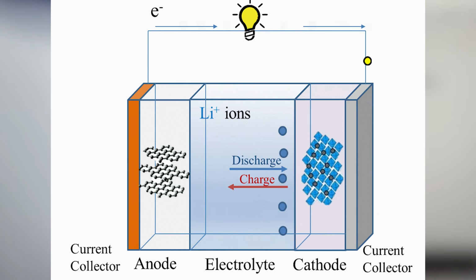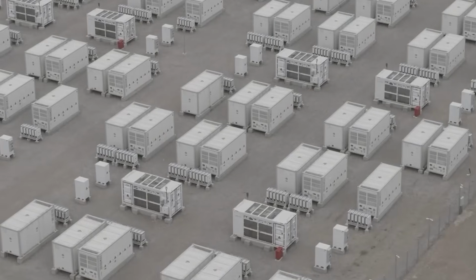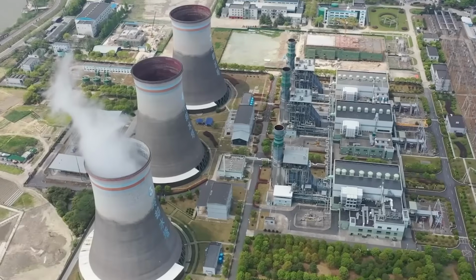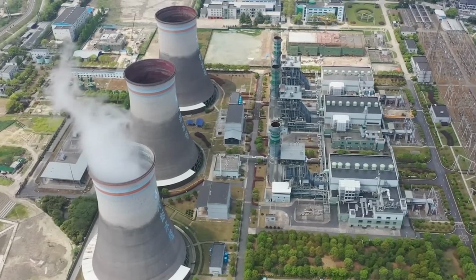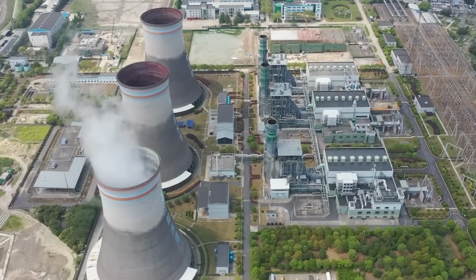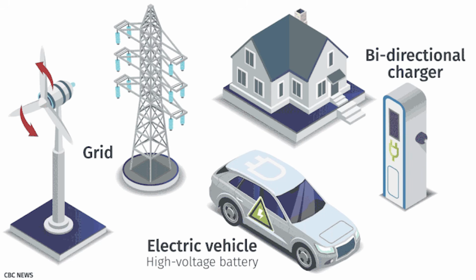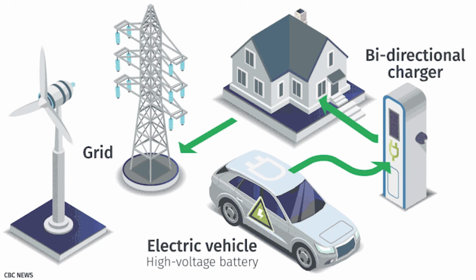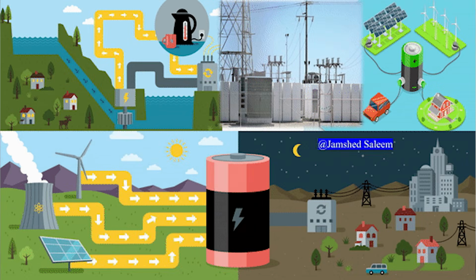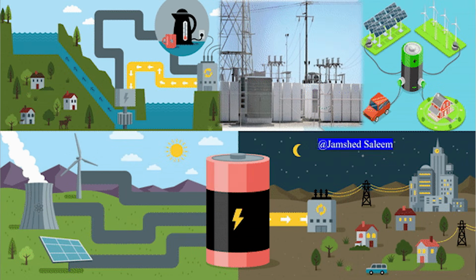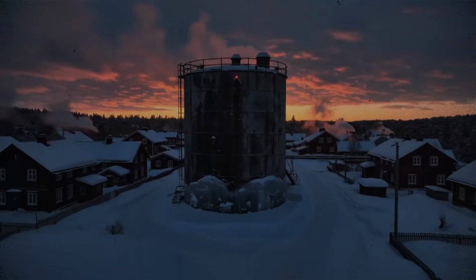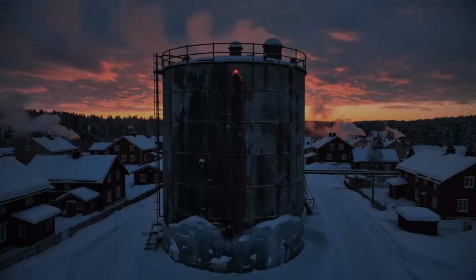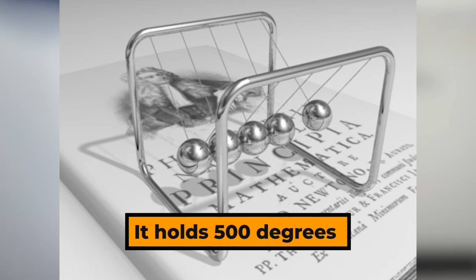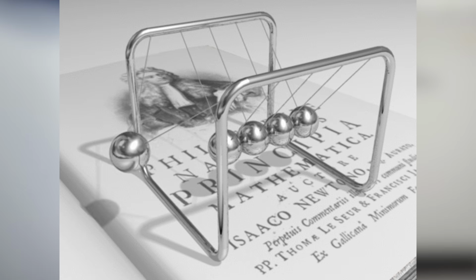Unlike a lithium-ion battery, which loses 2 to 3% of its rated capacity every single year through irreversible chemical degradation, sand does not degrade. You can heat it and cool it 50,000 times across decades, and it remains chemically and structurally identical. No dendrite formation, no thermal runaway risk, no cobalt, no lithium, no rare earth minerals, no battery management system watching for cell imbalance. Think of the insulated vessel like an enormous thermos flask. Instead of keeping coffee hot for 8 hours, it holds 500 degrees of thermal energy locked inside a steel silo for weeks.